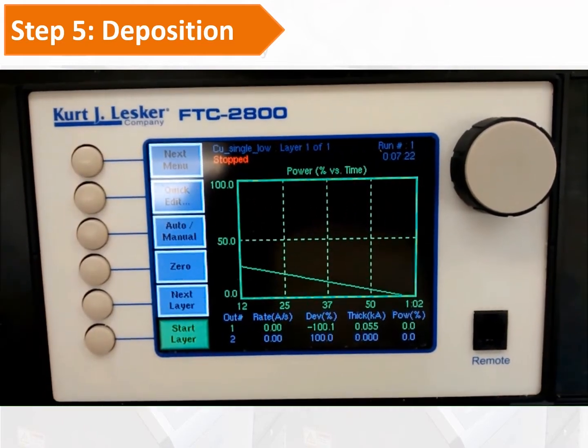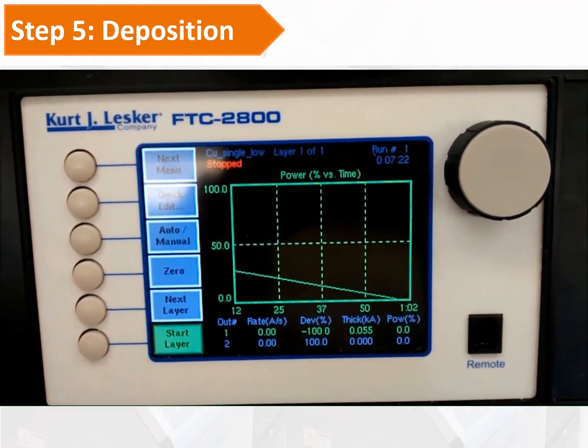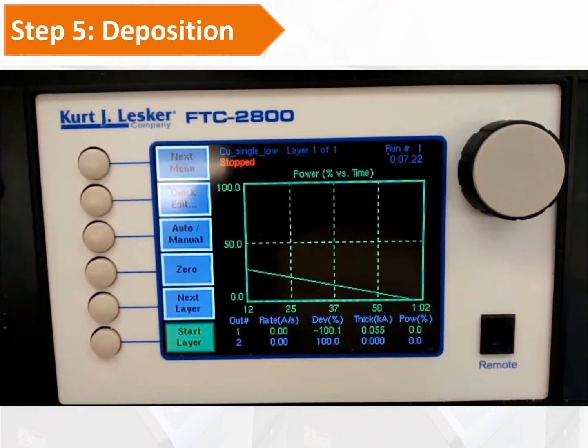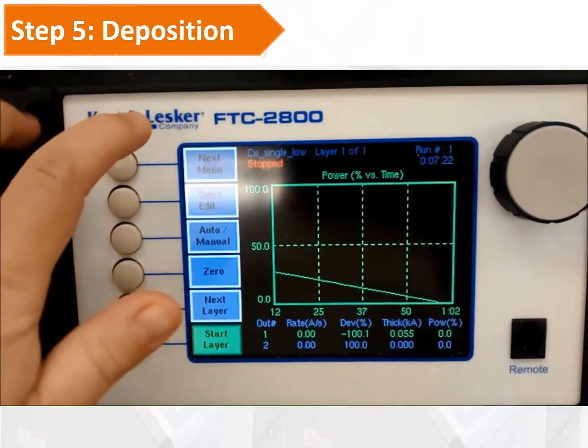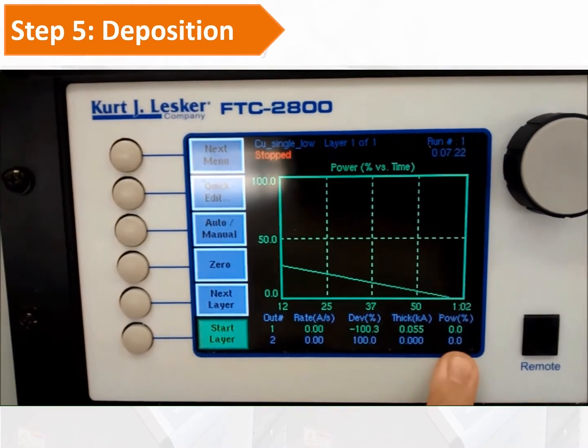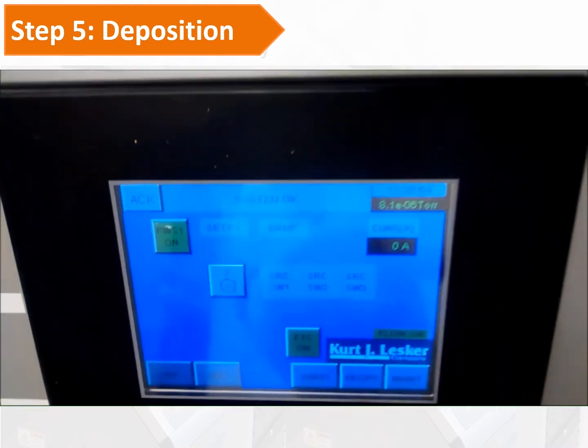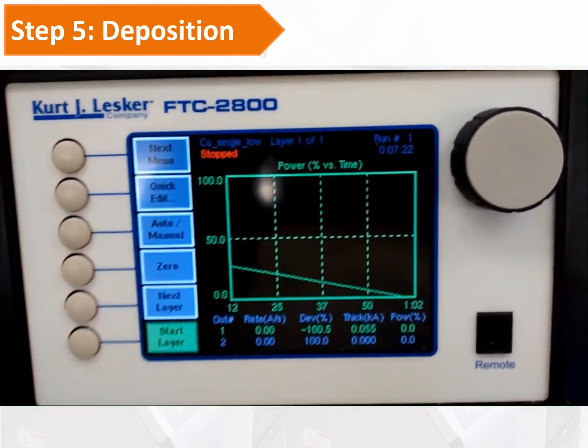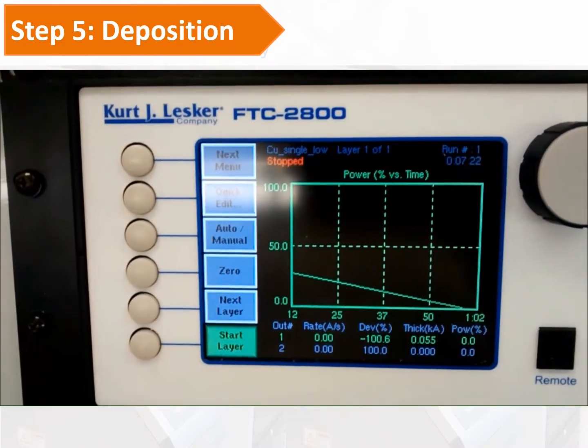And you may also find on the screen that it shows stopped, letting you know your process is stopped. So if you still need to run another layer deposition, you can set the pocket number in the film menu, and also set the final thickness in the process menu, and press start to run another layer deposition. So that's what we're talking about for these deposition procedures.